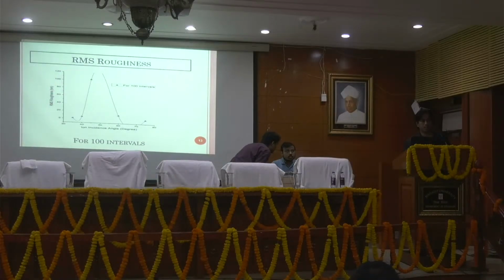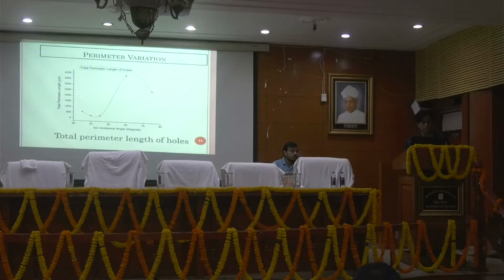These are the results for the RMS roughness, that is the roughness of the surface which is created by the ion beam source. We have taken it for 100 intervals. This is the perimeter variation, meaning the whole perimeter. The whole perimeter is also important because the lower the perimeter, the efficiency is reduced. So we want to enhance the perimeter so that the efficiency of the material can be used for various applications. We see that after the 45 degree to 60 degree incidence angle, the perimeter has been enhanced greatly.